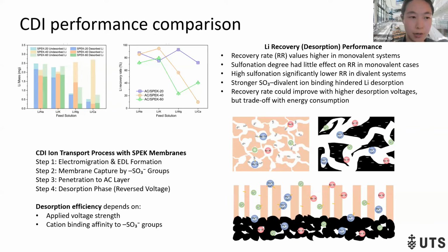And the figure shows the CDI ion transport process with the SPK membrane. First, step one is the electromigration. The cations migrate to the membrane surface under the electric field and form an electrical double layer. And then some cations bind to sulfonate groups inside the SPK membranes. Divalent cations show stronger binding affinity. Remaining cations pass through the membrane to reach the active carbon layer, absorbed in pores and interparticle spaces.